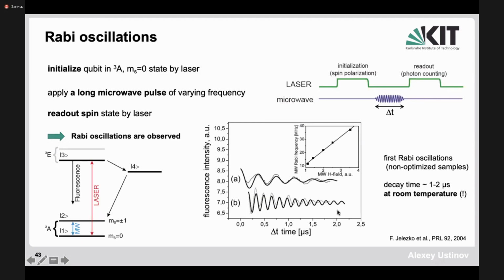So basically you do this standard manipulation, but what is magic about it really is that you could do it even at room temperature. If you go to low temperature, to a few Kelvin or even below, then of course the coherence times improve, but still you can have very appreciable coherence of the order of a few microseconds even at room temperature. So one doesn't really need a sophisticated setup to decrease temperature, but rather sophisticated enough to use those lasers, operating fully at room temperature. And therefore, this was really a very attractive platform to think about quantum computing.